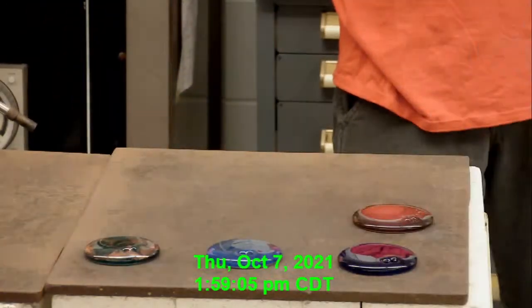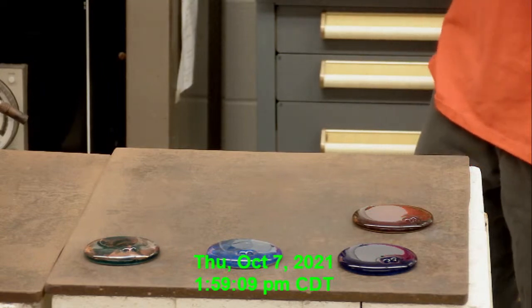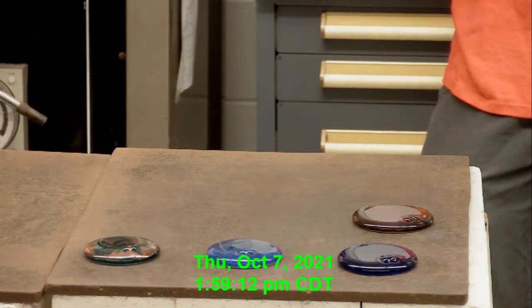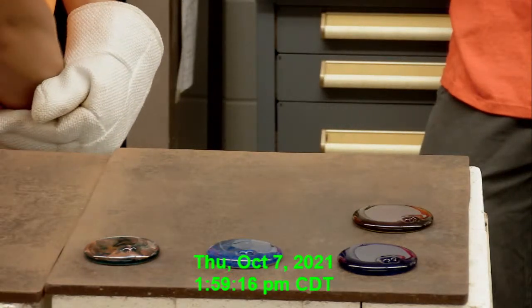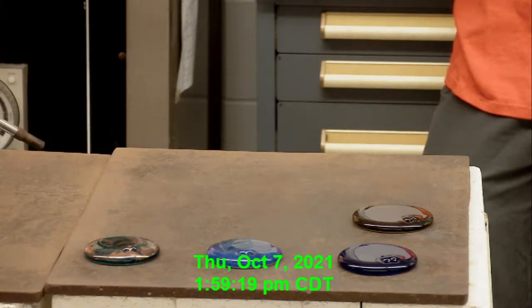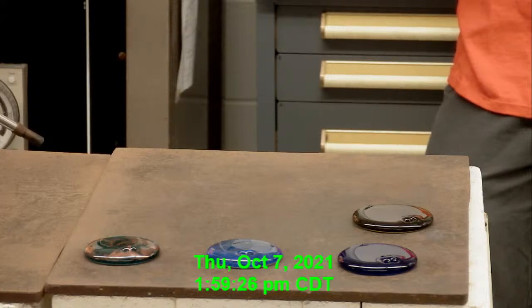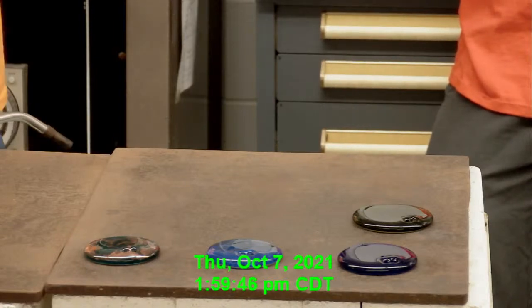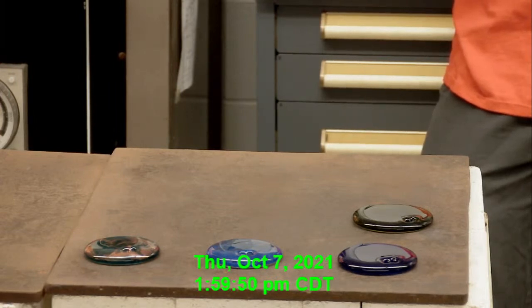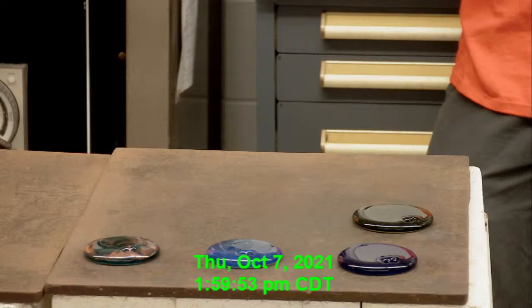All right, so there are some interesting effects that happen while glass cools. They call it the temperature at which the final color strikes, the striking temperature of the glass. Sometimes the color won't pop in until it seems like it's cooled down quite a bit, and the color darkens. The reason for that is the metal sits in the middle of 4 to 6 oxygen atoms. To begin with, the oxygens are moving so quickly they haven't formed coordinated bonds with the metal. But after it cools down enough, those bonds form, the cobalt's in its final placement, and that makes that color more permanent.